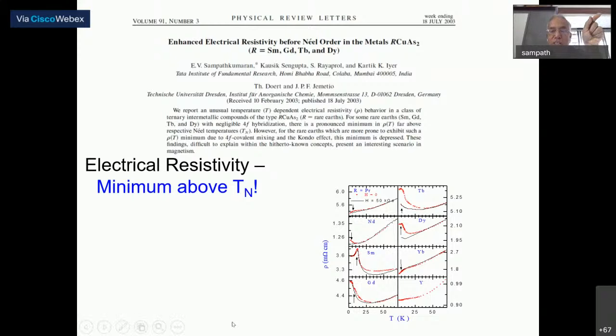Almost all the members of the family, barring cerium and praseodymium. In cerium, praseodymium, you find a very huge upturn before magnetic ordering. If the magnetic ordering temperature is this, you see a very huge upturn here. You could see it not only in gadolinium, also dysprosium, terbium, also samarium, everywhere. So this seems to be quite common, except people have not noticed it.